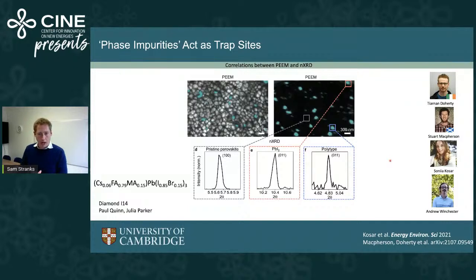And so the question is, what are these impurities and what are these traps and what are these trap clusters? So here we're correlating structural measurements with these trap measurements. So this is again taking a PEEM image of these trap states, and that's what's shown in blue here. And then we take them to the Diamond Light Source, the Diamond I14 beamline, which is the nano X-ray diffraction, scanning X-ray diffraction beamline, so we can look at nano X-ray diffraction patterns from these materials.